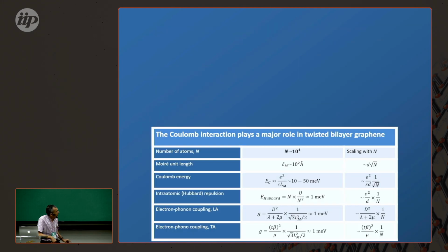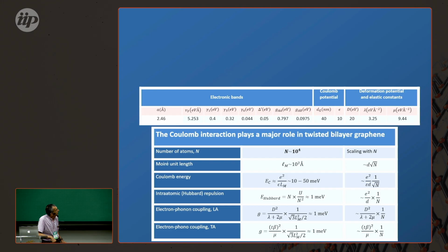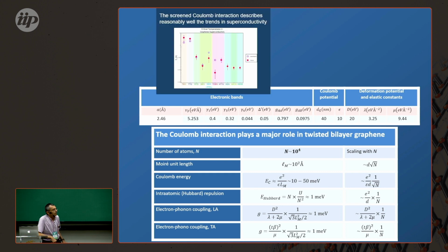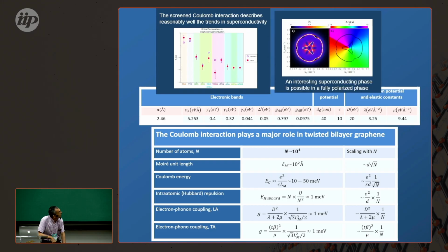So let me summarize. Yes, I wanted to tell you, if you classify the interactions of twisted bilayer graphene, you realize that the Coulomb interaction definitely is there and is very strong. You use a very conventional and standard set of parameters, and you get a trend for the superconducting critical temperature, which fits reasonably well the experiments.